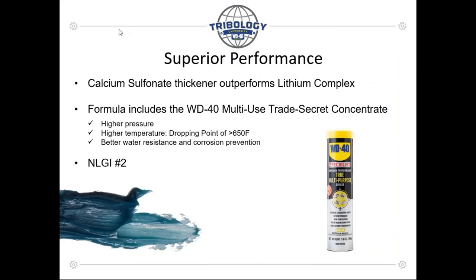I mentioned calcium sulfonate being a premium thickener. But one of the unique attributes of the product that we're offering is the fact that it uses the WD-40 multi-use trade secret concentrate that you find in the blue and yellow can. And it actually gave us a property. There's a bearing corrosion test for greases. It was the only one to pass the more rigorous bearing corrosion test where we added 10% salt water instead of 5%. It passed that as well. And so we're very proud of the product that we developed. We really believe it to be a true multi-purpose grease.